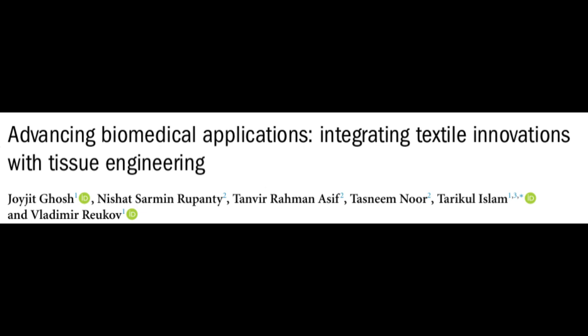That's key. Definitely. Woven or knitted scaffolds using materials like PLGA combined with elastin are designed to mechanically mimic the elasticity of the dermis. And incorporating skin cells, keratinocytes, and fibroblasts into these textile scaffolds significantly enhances the regeneration process. Moving inside the body now, textile structures are also proving vital for vascular replacements, right? Blood vessels. Yes, creating functional small-diameter blood vessels is a major challenge.